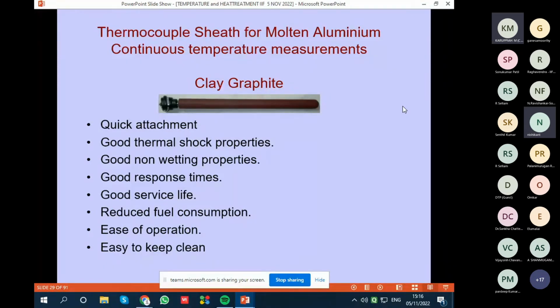Earlier, silicon carbide was used, but it was prone to breakage and very expensive. Some people still use cast iron, but cast iron is not recommended because cast iron has iron, which is not a friendly metal for aluminum, as you know. So most popular is this clay graphite sheath. It can be used very heavily, and I showed you all the advantages here. It has a very good response. It does not wet with the aluminum.